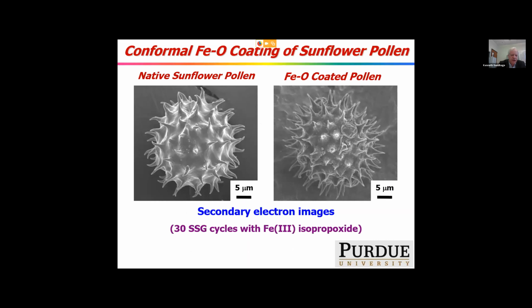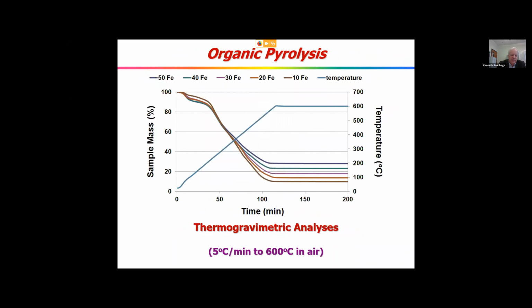And so what you see here on the left is a pollen particle again, sunflower pollen. On the right is after 30 surface sol-gel cycles with iron isopropoxide. It's a very conformal coating. If you take that and fire it in a TGA, you get different amounts of weight loss, of course, depending on how much of a layer you put on, 10 or 50 cycles.